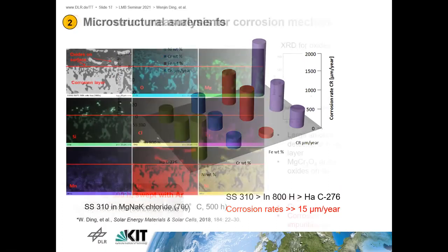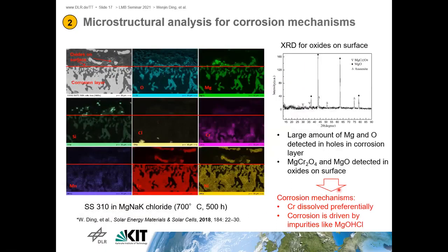So from the SEM and EDX analysis of the cross section of the samples, we found the corrosion mechanisms for the conventional alloys. First, the chromium element is dissolved. And also important, the corrosion is driven by impurities like the magnesium hydroxide ion in the salt. I think this is also possible for the molten salt electrolytes for the liquid metal batteries.